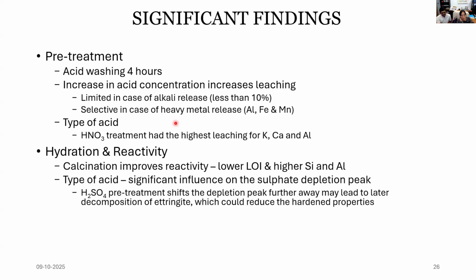And coming to the hydration reactivity studies, we could understand that calcination, obviously, improves the reactivity by reducing the loss on ignition of the system and increasing the amorphous silica and alumina in the system. And when it comes to the specific type of acid treatment, if we are going to pre-treat the ash with sulfuric acid, we need to be very conscious, because sulfuric acid treatment leads to a higher amount of sulfate in the ash. That might result in decomposition of ettringite at a later stage, which we can observe from the hydration peaks. This might lead to some hardened-property problems in the later stages.